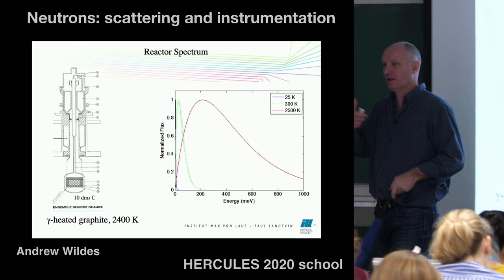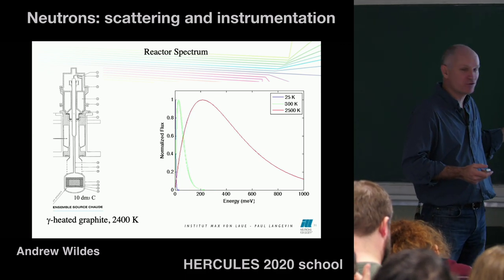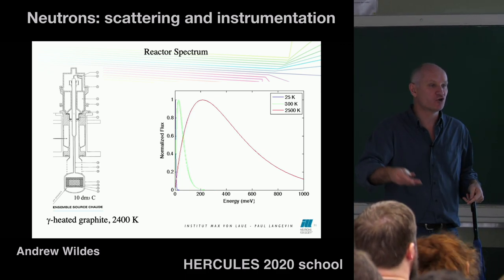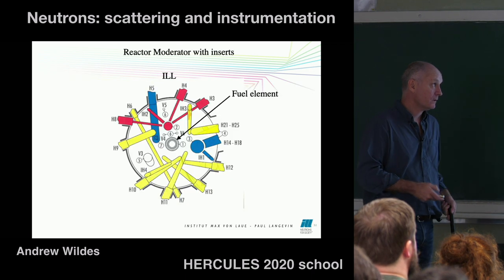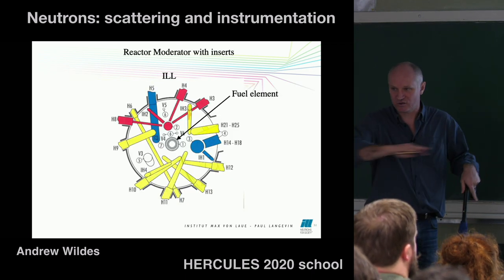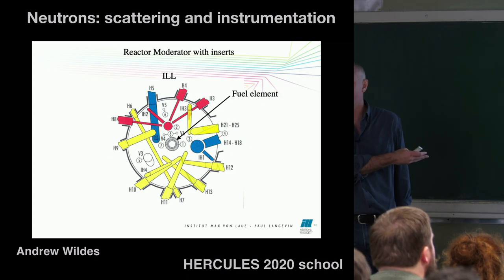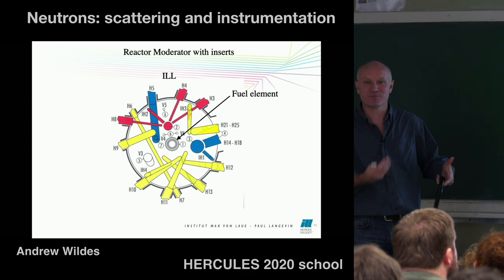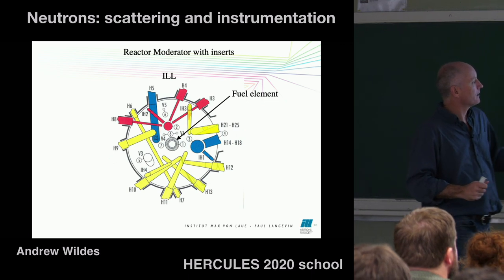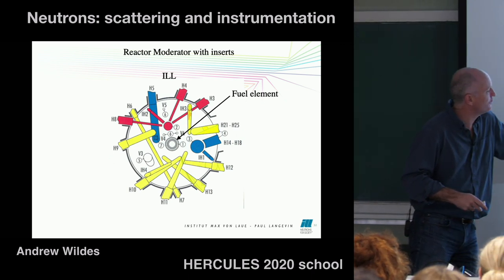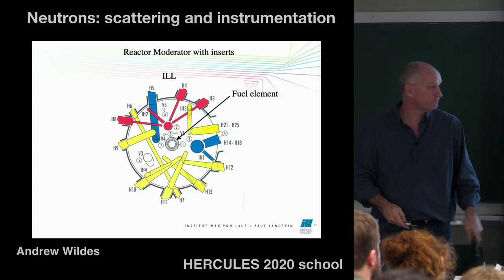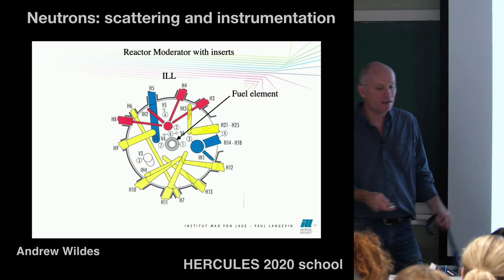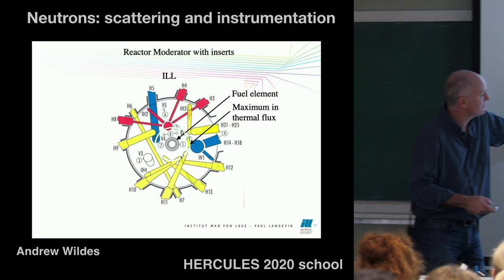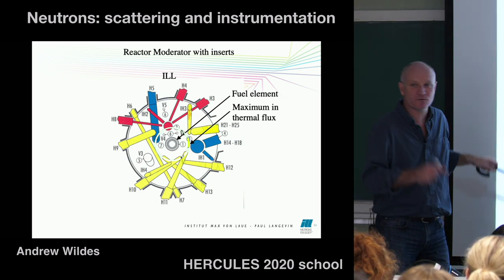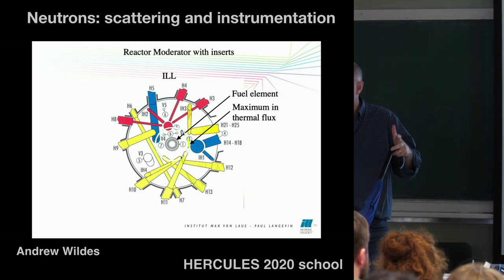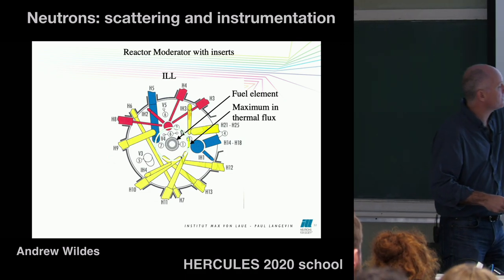If you want to look at things like liquids or glasses, you would point your instrument at this source, and then you get a lot more neutrons in the energies that you wanted. So if you look now to a slice through of the ILL, of course a lot of reactors have similar sorts of setup, but I'm showing the ILL because we're best. If you look here at ILL, you've got a fuel element in the middle, very centralized, and then you've got all these sort of beam tubes around. If you could plot the distribution of neutrons as a function of the radius, there's a spatial aspect to this as well.